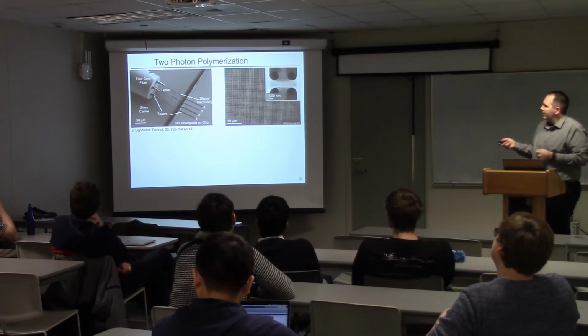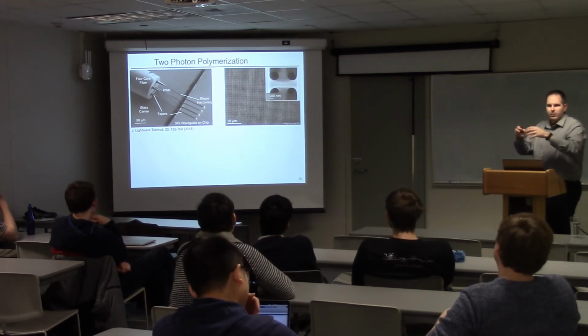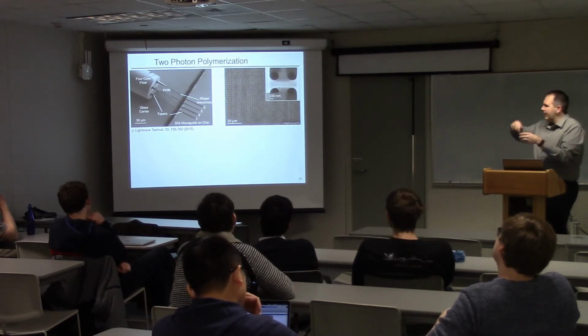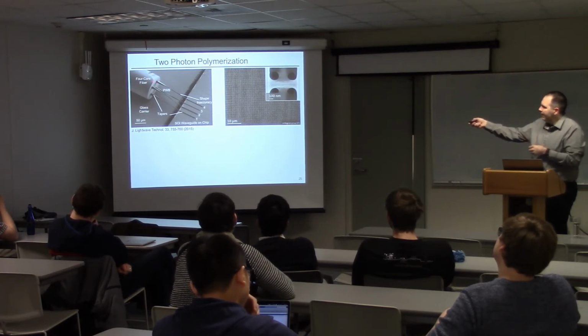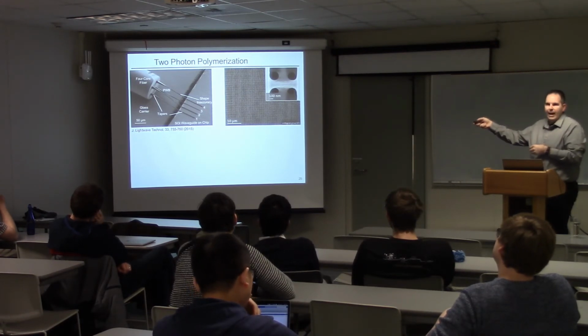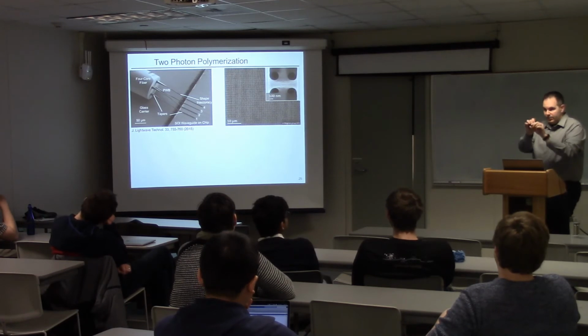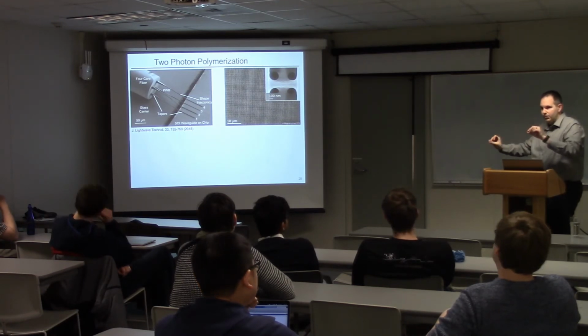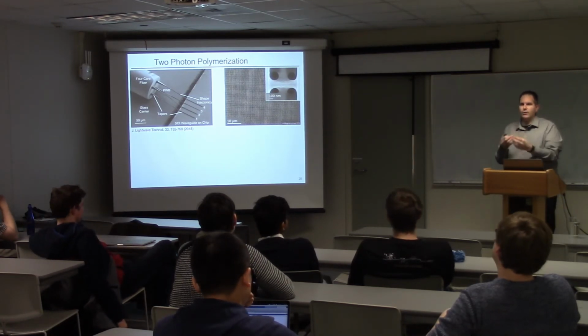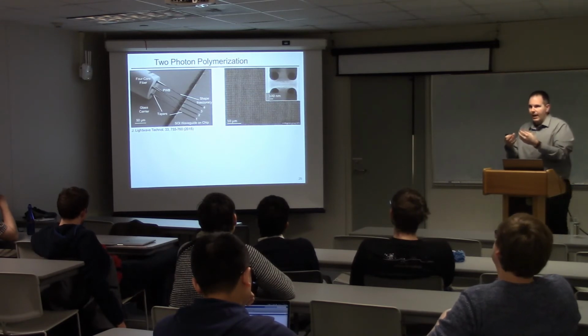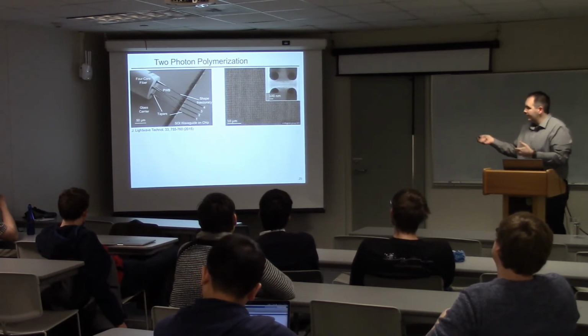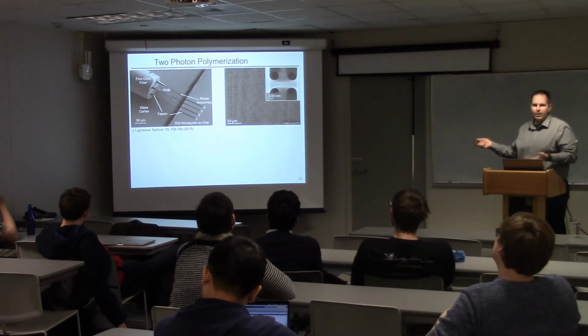And so here, they would have put this polymer overlaid over top and come in with the laser, and the laser would have traced the area from here to here. And that area, and only that area where the laser beam was focused and traversed through, would have gone through that chemical reaction that hardens the material, and then they could develop it and wash it away. And so here, this is kind of photonic wire bonding.